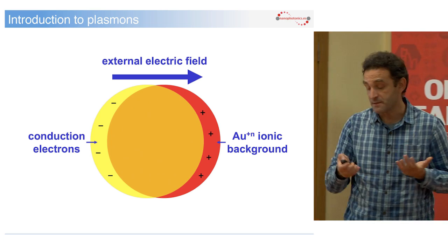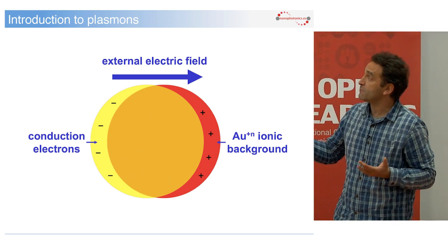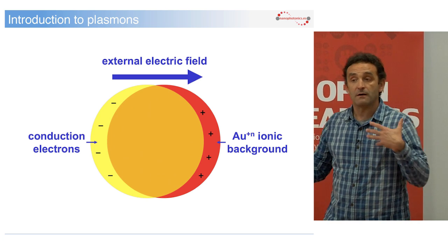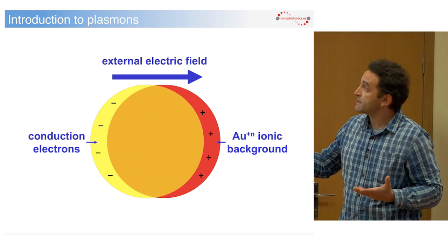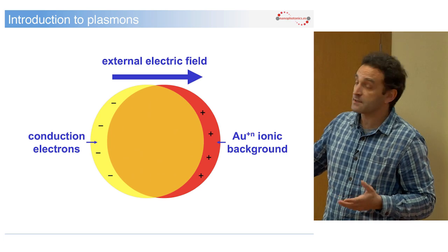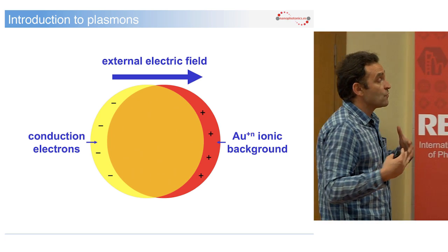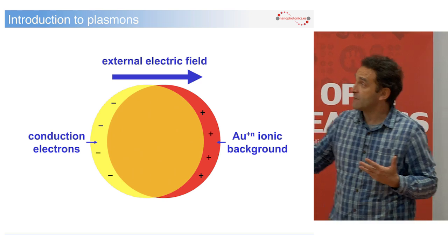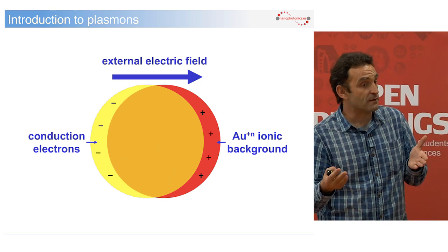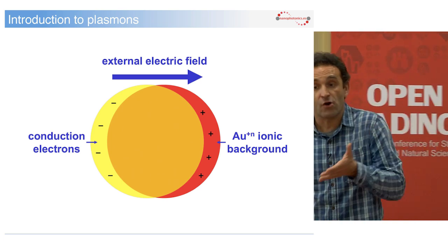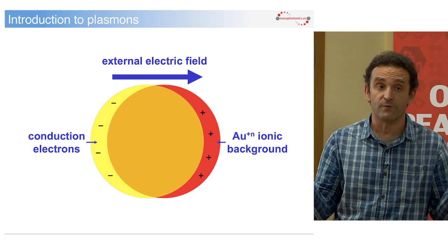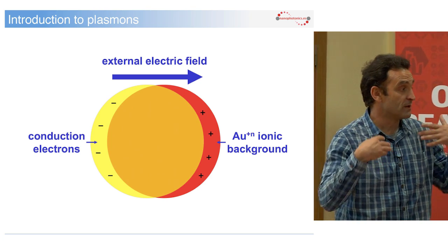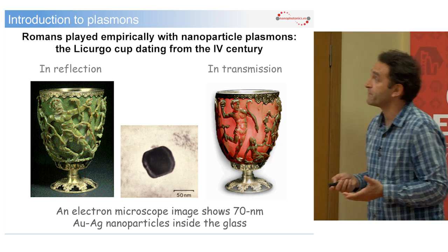And now what happens is, when you have materials like gold or silver or noble metals, where the size of the particles is tens of nanometers, then you can have resonances in the visible and the near infrared, and they are useful for technology because those are the ranges where we use them for sensing, for optical signal processing, etc.